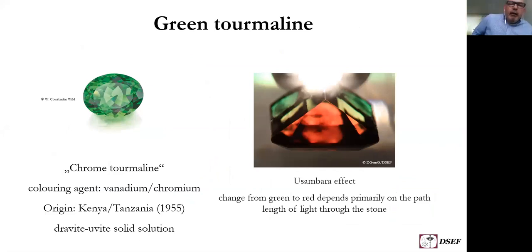Another green tourmaline, which is also very attractive, is a green tourmaline that is not colored by iron, but one which is colored by chromium, but more generally by vanadium, a combination of vanadium and chromium, a stone which first appeared in the trade in the late 1950s and originates from Kenya and the border between Kenya and Tanzania. And this is collectively known in the trade as chrome tourmaline. Although in most cases, the tourmaline is predominantly colored by vanadium. Now this stone, from a mineralogical point of view, is a mixture, or as we say, a solid solution between the tourmaline minerals dravite and uvite.